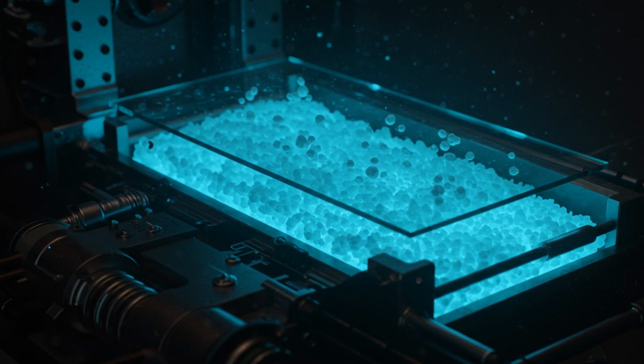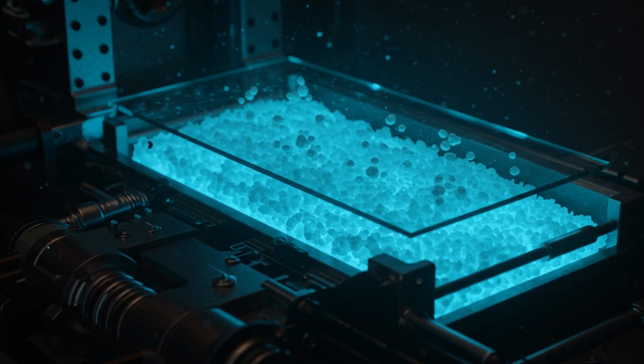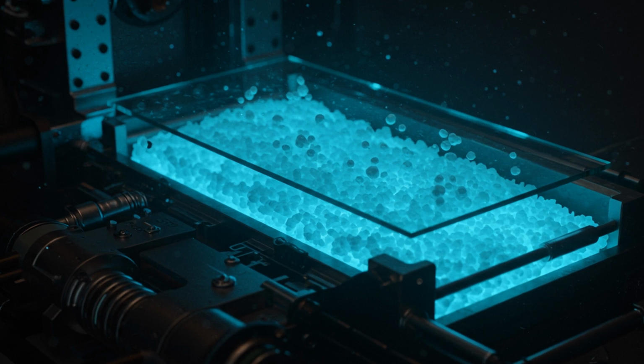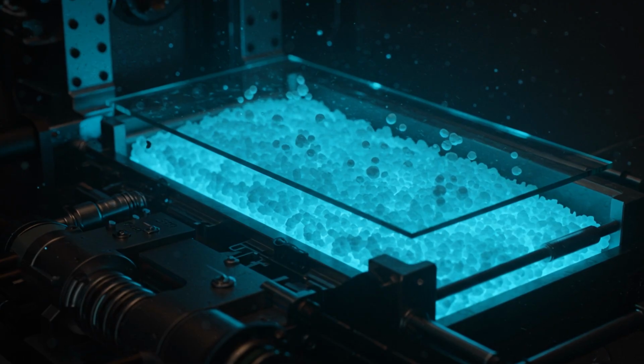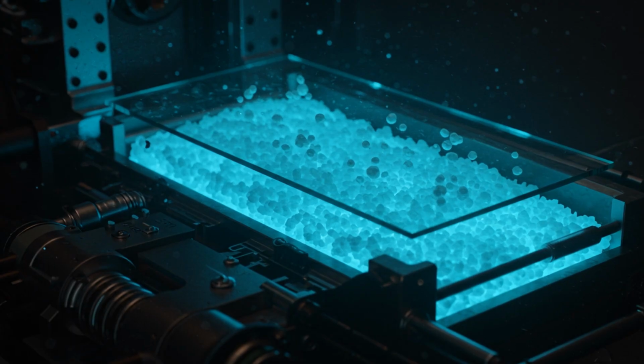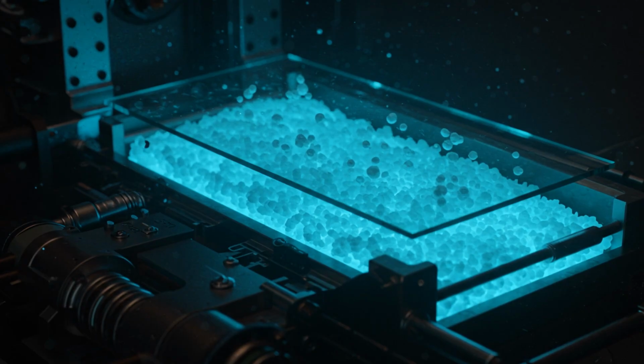This is essentially preloading the glass with pressure. When you bend the display, it has to overcome this internal compression before it can even begin to experience tension. It's like armor plating at the molecular level. This process increases the surface hardness and makes it significantly more resistant to scratches and impact. After several hours in the bath, the glass emerges with a structural integrity that belies its paper-thin profile, moving one step closer to your pocket.